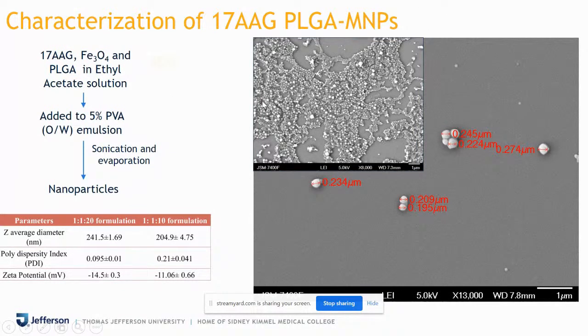The first one is a full bird's eye view of the nanoparticles, where you can see the small spheres. And then we actually measured the particle size of each of these particles, which were close to around 200 nanometers. So this confirmed using scanning electron microscopy that we have synthesized nanoparticles. But now the question was whether they had drug in them, as well as the magnetic component, that is Fe3O4. So we need to characterize them using other techniques so that we can answer these questions.